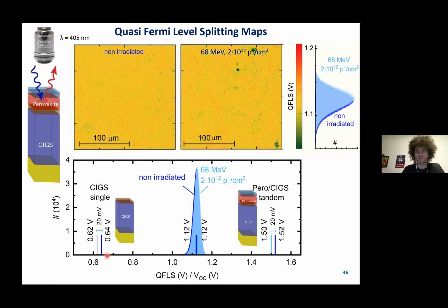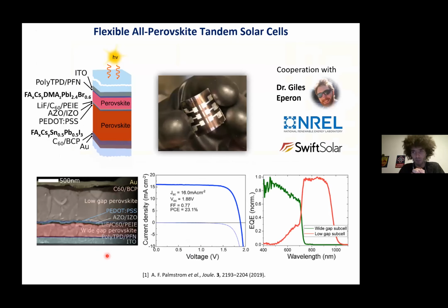With that, I would like to come to the next big tandem, which is perovskite-perovskite tandem. So now, in contrast to perovskite silicon, perovskite-perovskites are all thin-film. So in this case, this is an all spin-coated, all solution-processed perovskite-perovskite tandem by Dr. Giles Eperon. And he's using a formamidinium, cesium, DMA, lead iodide bromide composition for the wide gap perovskite, and then a 50-50 lead-tin-based composition for the low gap perovskite.